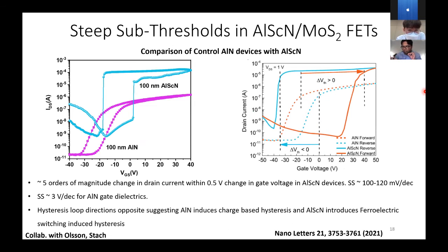So to further prove this is still a ferroelectric switching effect, we made similar devices, but on just aluminum nitride, not on aluminum scandium nitride. And we were able to see hysteresis in them too, but this was clockwise hysteresis. Clockwise hysteresis means it's simple charge trap based hysteresis. Counterclockwise hysteresis is actually more for ferroelectric switching.